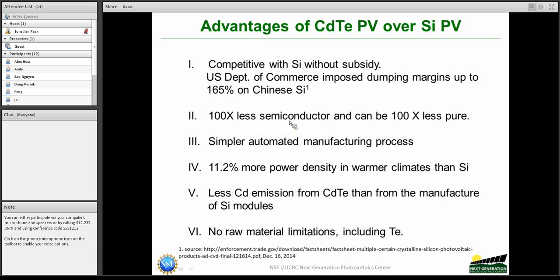And for semiconductor reasons, the cadmium telluride requires 100 times less semiconductor material, and the semiconductor can be 100 times less pure, which provides a significant advantage. And it's a much simpler automated manufacturing process, and I will briefly describe the process for making cadmium telluride versus silicon next. And for the same module area, cadmium telluride produces about 11.2% more power than silicon, and this has to do with the temperature coefficient of the two semiconductors. And interestingly, there is less cadmium emission from cadmium telluride modules than from the manufacturing of silicon.